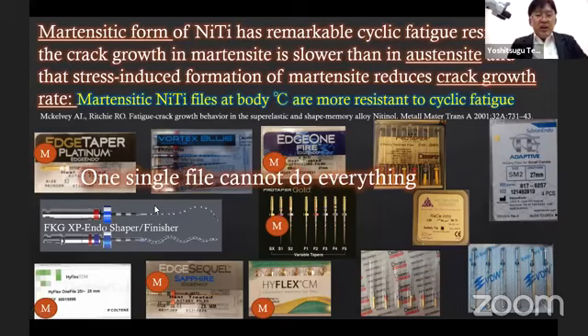So again, another consideration is this. The martensitic form of nickel titanium instrument has remarkable cyclic fatigue resistance. The crack growth in martensite is slower than austenite. So if you want to prevent fracture, you need to use the martensitic form of nickel titanium instrument. In other words, you need to use martensitic phased nickel titanium instrument. Remember, keep in mind, you need to use the instrument below the austenite finish temperature, so you can maintain the flexibility of the instrument.